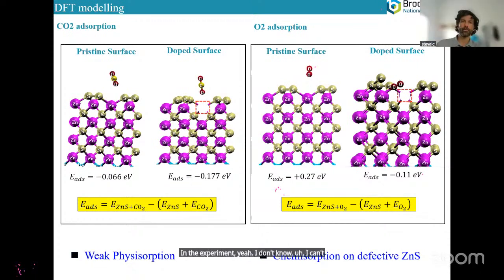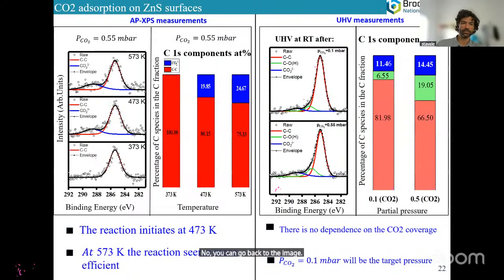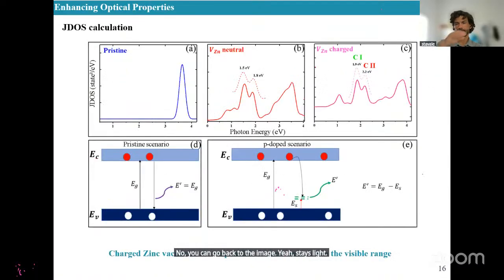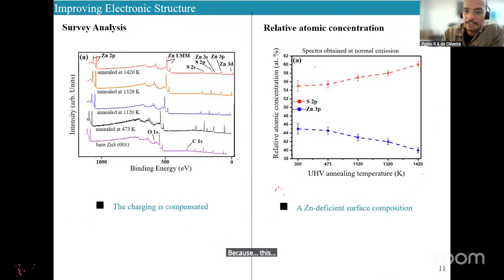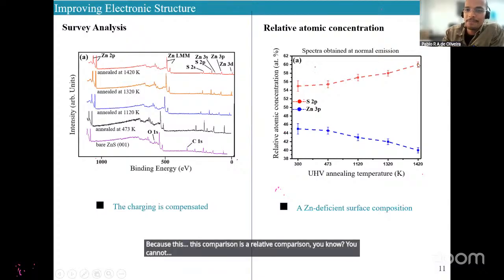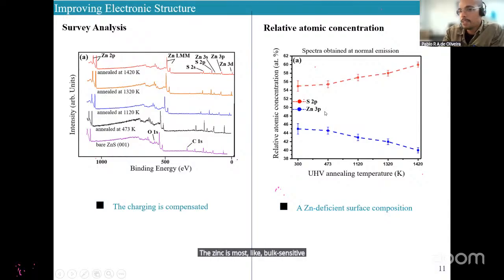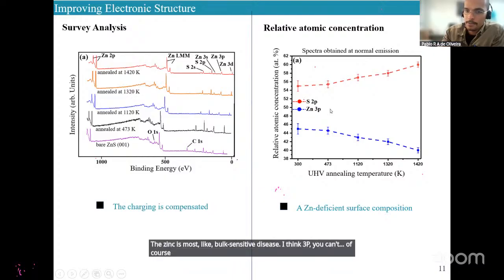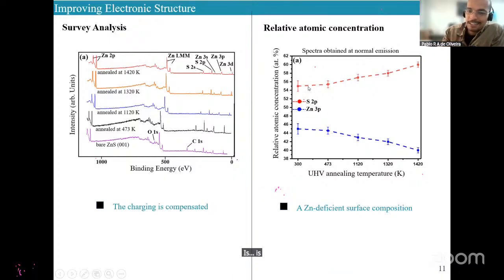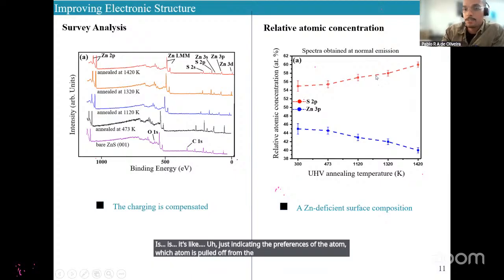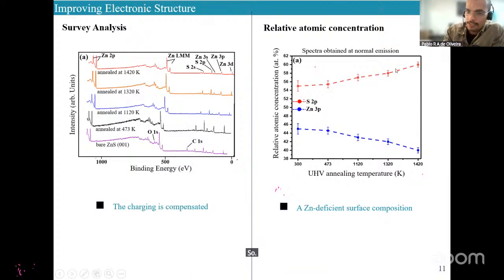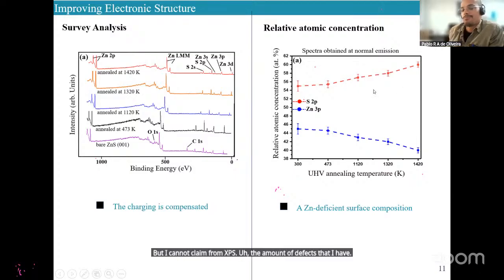You can go back to the image. Yeah, stay on the slide. He's mentioning that this comparison is a relative comparison. You cannot claim that you have like 10% of sulfur over the zinc because the zinc is more bulk sensitive. This is zinc 3p. Of course you have this signal for the surface, but it's just indicating the preference of which atom is pulled off from the surface, sulfur or zinc. So preferentially sulfur stays in the surface and zinc is pulled out. But I cannot claim from XPS the amount of defects that I have. Okay.